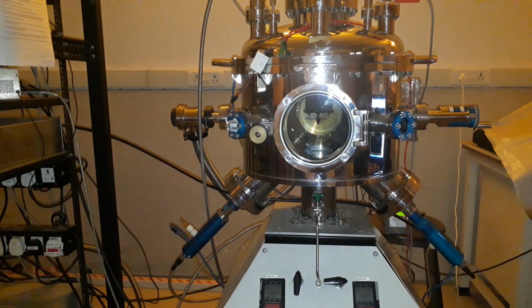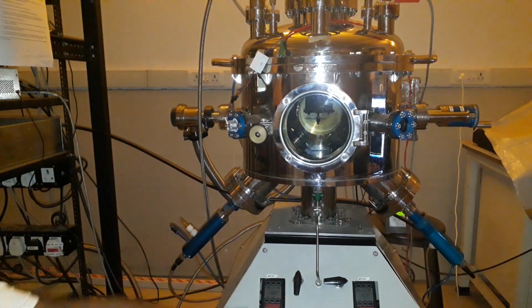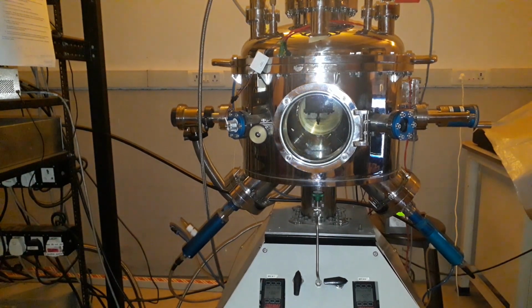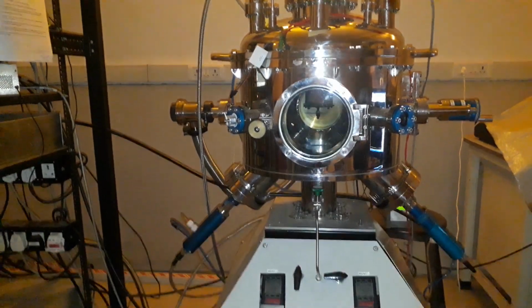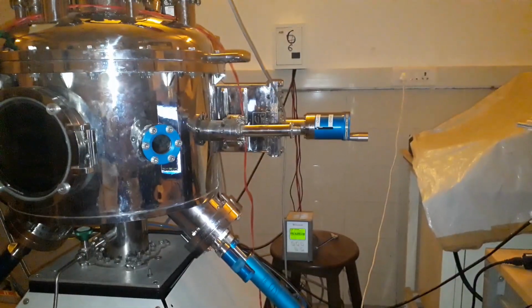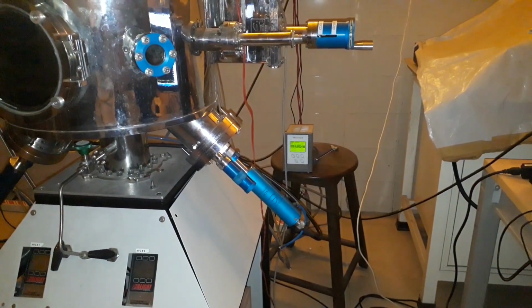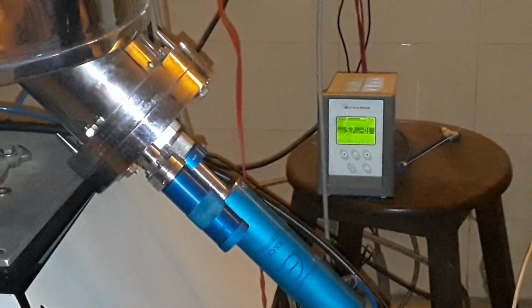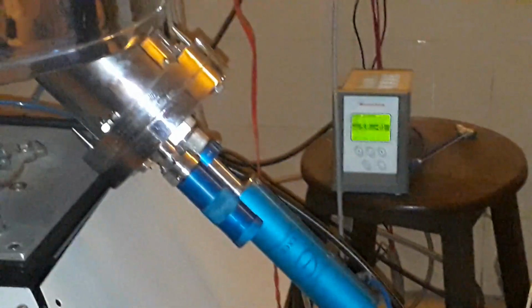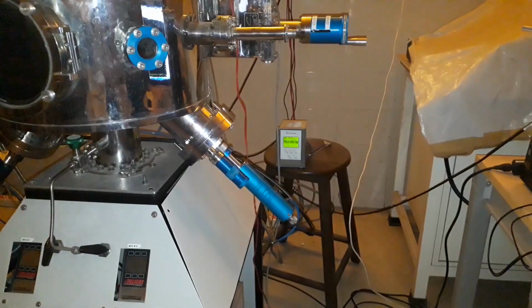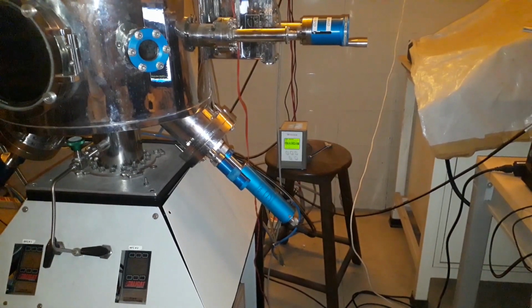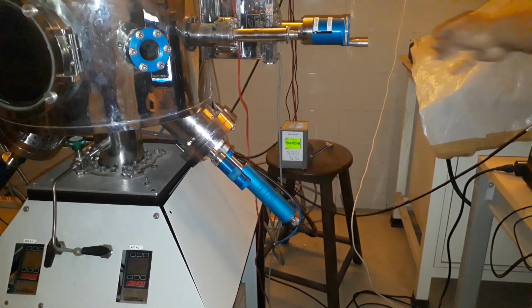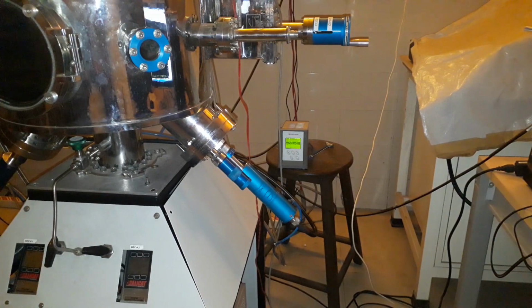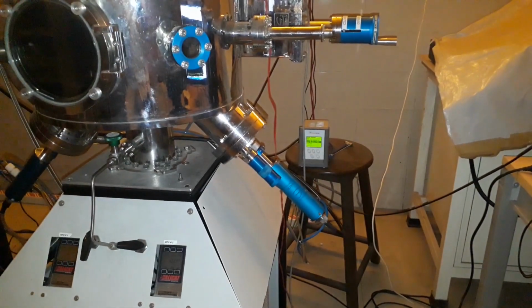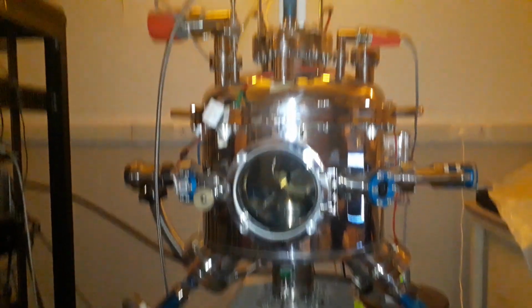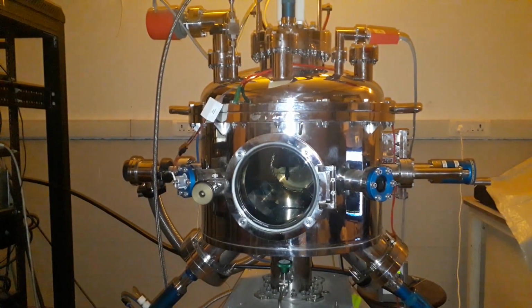So right now it is set at 30 SCCM, temperature is 23 degrees, and I have put the turbo on standby mode. If you see there, on the meter, the pressure is 5.7 times 10 to the minus 1 millibar. Sorry, it is standby mode. I have closed the gate valve as much as possible to control the pressure. Otherwise, it's too much load on the turbo pump, which is not good. So everything is set nice and fine.